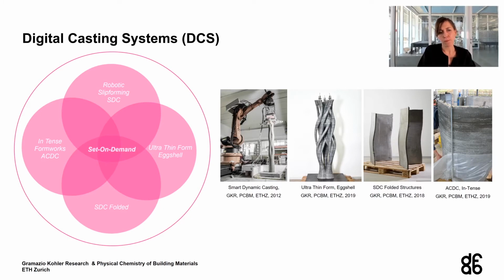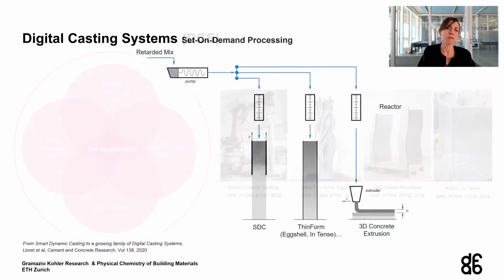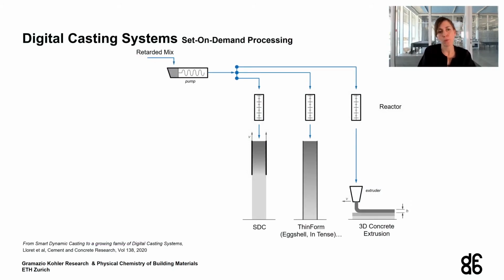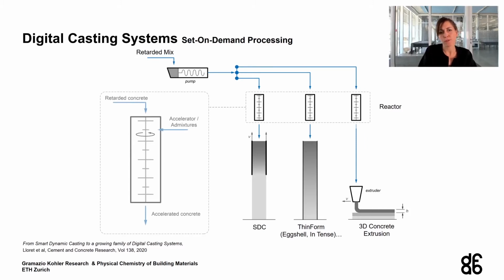They all have the same thing in common, which is using set-on-demand concrete. And what does set-on-demand concrete mean? Well, in fact, we have a retarded mix, which is pumpable, and then it's placed into a reactor into which accelerating admixtures are dosed at specific intervals. For smart dynamic casting, we cast a self-compacting concrete into a mold that moves, while for thin formworks such as Eggshell and In-Tense, we fill a still-standing formwork, which is not moving, but for Eggshell is printed simultaneously and for In-Tense is supported very weakly.